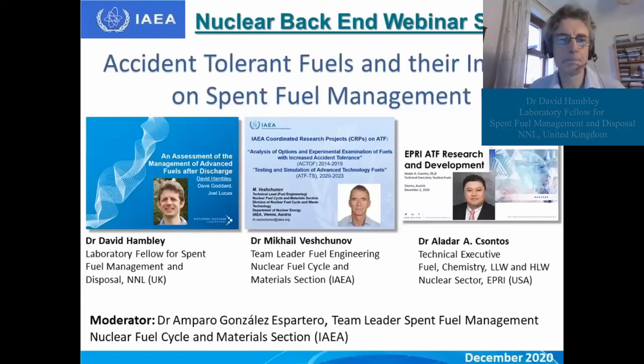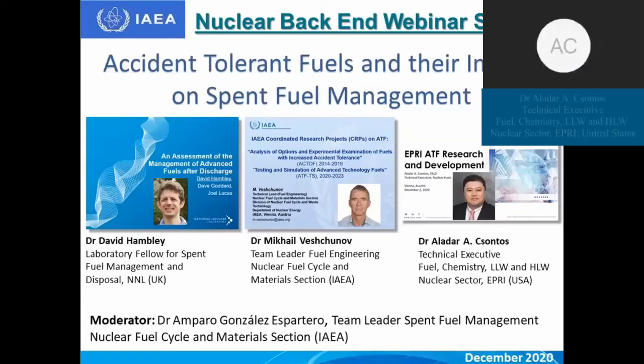So can I add a few things, David, to that? We talked about this significantly during the 2019 workshop, and what we found there was the addition of flux traps within the canisters, if the enrichments and the criticality analysis were substantially different. That would create a design change, and also, as you mentioned, David, possibly a reduction in the number of assemblies per canister to load. That was found to be very problematic by a lot of folks in the meeting. And so that was one where the vendors said that there may be ways around that, but of course it might be dependent upon a lot of information and data that would need to be provided in terms of what the expected end-of-life spent fuel characteristics would be. So that was an area of importance.